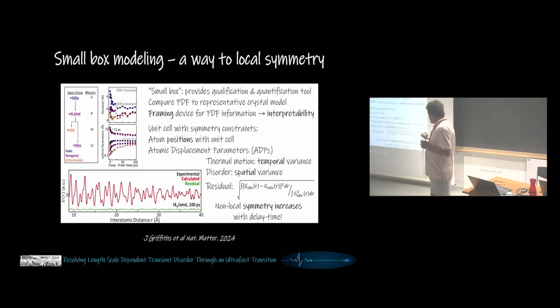Okay. The other thing that you can ultimately do is structural refinements on such data. So we have tried this. We fit a cubic model, a tetragonal model, an orthorhombic model, and another tetragonal model. And all of them fit the data, except that the cubic model never works. And the cubic model is the model that describes the equilibrium high temperature metallic regime. So that's one thing. The other thing is, it seems, according to this analysis, that the symmetry for the short delay times is lower than the symmetry for the higher delay times.